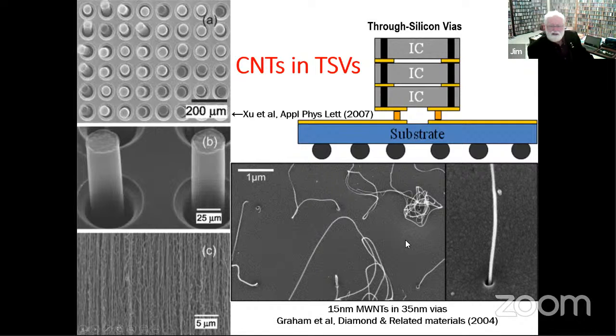There's an earlier result here from Infineon, I believe, where this is a single 15 nanometer carbon nanotube grown in a 35 nanometer via. So that certainly says that in principle, single carbon nanotube interconnects are a feasible, very, very high density interconnect in silicon, through silicon vias. It doesn't mention the problems of contact at the other end and everything else, or mass production. This is a demonstration of feasibility.